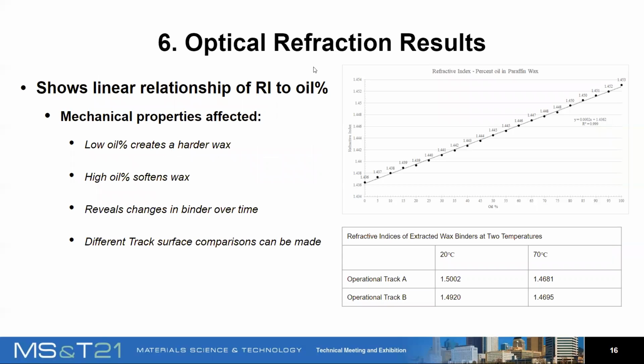Moving on here, this is the optical refraction results. We did some initial testing on some paraffin wax. We added oil to the paraffin wax and we can see this linear relationship. On the y-axis here, we have the refractive index and the oil percent on the x-axis. As you can see, as the oil percentage increases, the refractive index also increases. This is important because a low oil percent creates a harder wax, a high oil percent softens the wax, and you can see how this changes the binder over time.